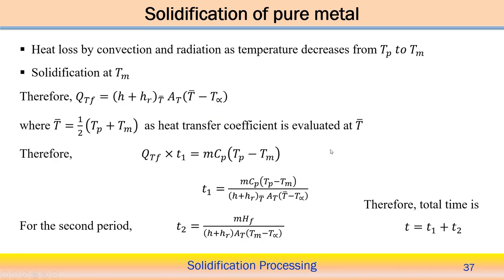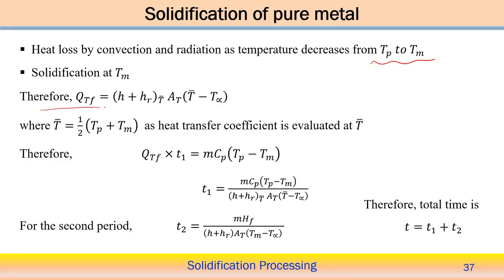From there we can find that heat loss by convection and radiation occurs as the temperature decreases from Tp to Tm. From the peak temperature to the melting point temperature, both convective and radiative heat transfer will be there, and then solidification occurs at Tm. So Q can be estimated as (h plus hr) times the cross section area times (T bar minus T infinity).